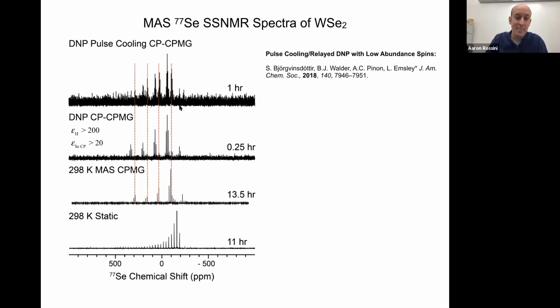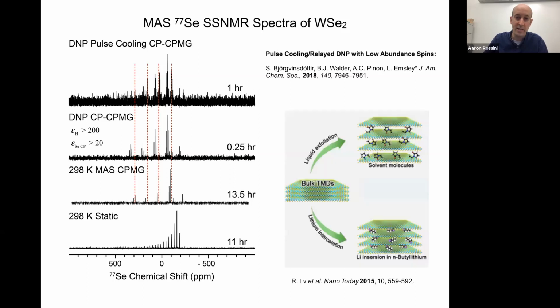So what we think is happening here is these peaks that we see in the normal cross-polarization experiment are either from exfoliated sheets that have partially dissolved in the tetrachloroethane, or the solvent molecules can actually intercalate in between the sheets, and this would give you more efficient cross-polarization, and proton spin diffusion would let you see those types of species. Then when we go to the pulse cooling, we're actually maybe able to polarize the bulk-like or aggregated sheets and see the selenium-77 NMR signals.